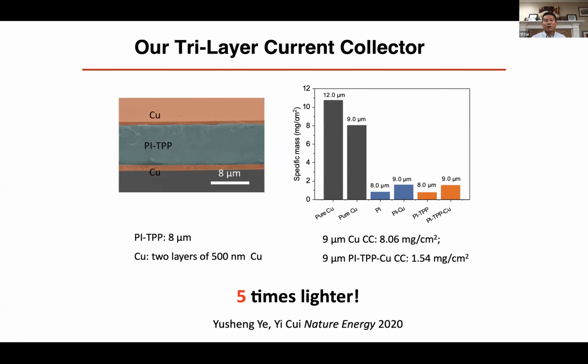But certainly the thing we need to consider is, is it conducting enough for fast charging? And with this 500 nanometer, we can roughly go to, you know, C/2 to 1C charging. If you want to charge faster, of course, the copper will need to be thicker. So using this 5 times lighter current collector, the energy density of the full battery per unit weight we can improve by close to 20%.